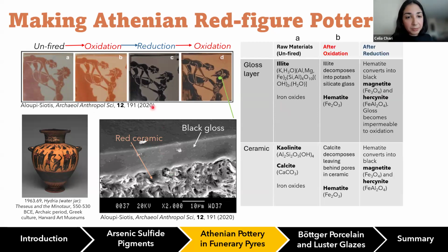Now in C, which is the next step here, we kind of see the opposite. There's reduction occurring. So hematite reduces into magnetite and hercynite. And in the ceramic, we see the exact same reduction of the iron oxides. And after this step, the gloss becomes impermeable to oxidation. And this is because it essentially solidifies, trapping those black iron oxides within that gloss layer.